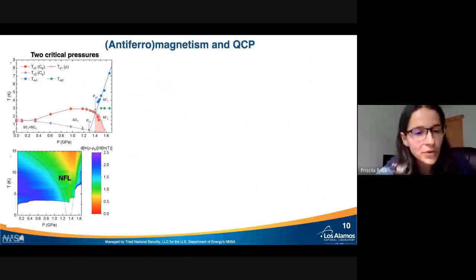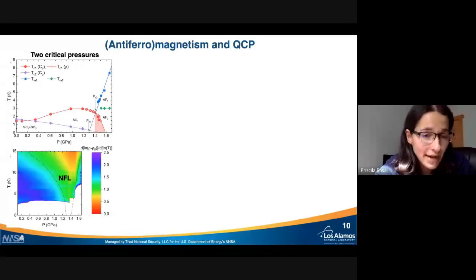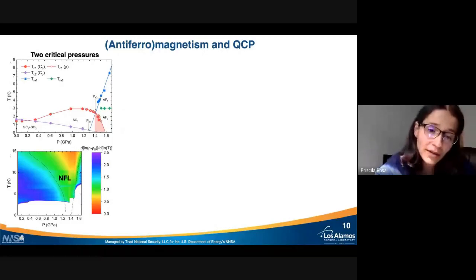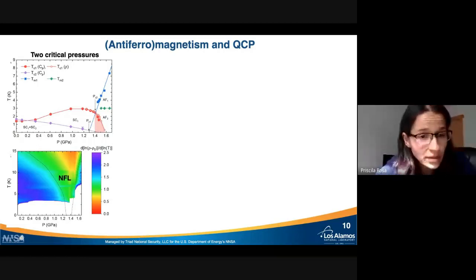And this is what I'm showing here. We have the phase diagram, temperature versus pressure, and we see the two superconducting transitions. Actually, they cross each other at low pressures, at 0.2 GPa, and one of them, the purple one, disappears, whereas there is a maximum at TC1 at the so-called critical pressure. So there are two critical pressures. PC1, here I'm calling the extrapolation of the magnetism, is what we call a quantum critical point. And PC2 is where magnetism and superconductivity merge, or are at the same pressure.